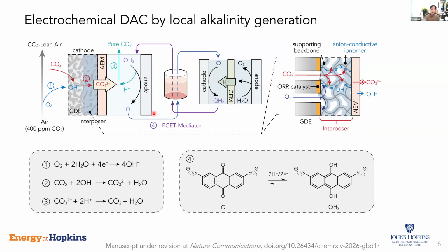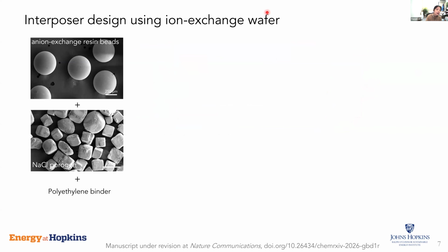So a big design principle for this interposer layer is that it has to be gas permeable and it has to be anionically conductive. So what we designed is that we take commercially available anion exchange resin beads, which are spherical particles like this, and we mix them with some sort of a porogen to create porosity, which in this case, we chose the simplest one, which is sodium chloride crystal.